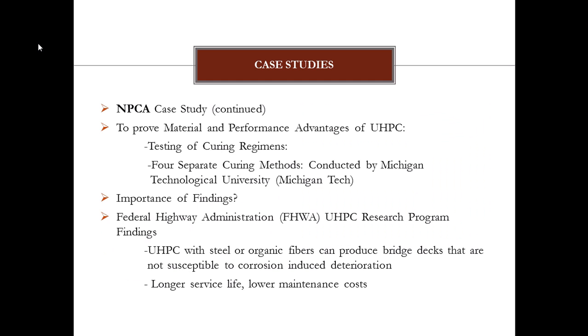of UHPC. The first test the NPCA case study cites was done by the Michigan Technological University, and it's a test of 4 separate curing methods. The first is a 48-hour thermal steam treatment at 90 degrees Celsius and 100% relative humidity. The second, ambient air curing. The third, a delayed thermal steam treatment, which is a 10-day delay before curing. The fourth is a double delayed, which is a 24-day delay before curing.